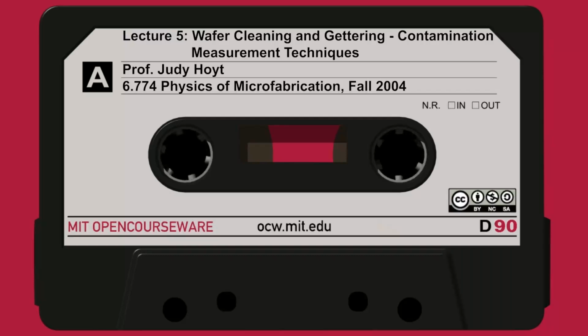This just shows thickness and the type of oxides that are used. The thickest oxides are used in the field. The field surrounds the active device region, so it isolates individual devices. Thinner oxides, like 100 angstroms, are used for gates or pad oxides. In fact, I put a little arrow here and showed it going down. Gate oxides today in the highest performance devices are a lot thinner than when this textbook was written, more like 20 angstroms. So they're actually down in this range of tunneling oxides. And finally, the very thinnest oxides are those chemical oxides that result from RCA clean, as we talked about last time, that are grown chemically rather than in a hot furnace.